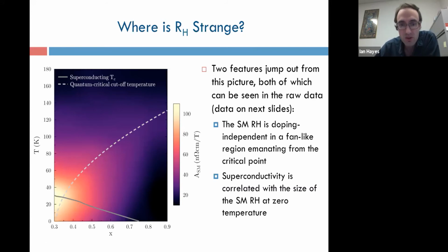So if you go just beyond the superconducting dome at low temperatures, you see none of this decreasing RH with field, you see pure H squared. You can recover the decreasing RH with field if you go to higher temperature, but specifically the low temperature part of the Hall coefficient seems to be strongly correlated with superconductivity.